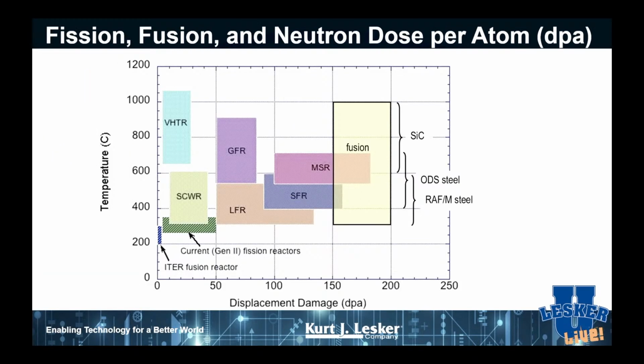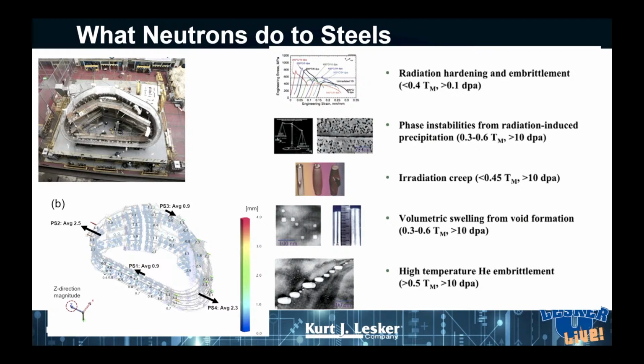And so your ITER reactors, your current fission reactors are sort of down in the sort of 10 displacements per atom over their lifetime. Fusion reactors are now up at around 150 displacements per atom over a 5-year period, not a 30-year period, but a 5-year period. Okay, so the lifetimes are much, much shorter. The damage is much, much more severe. And even at small doses, even at small displacements per atom, you see radiation hardening. You see the metals get brittle.